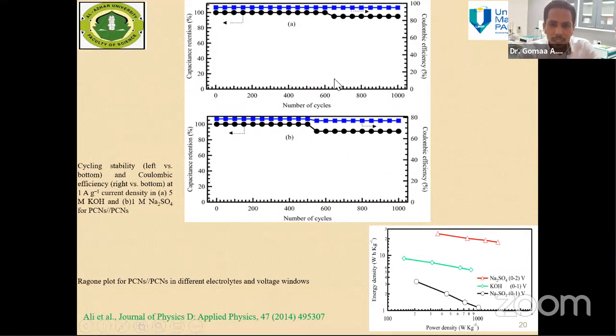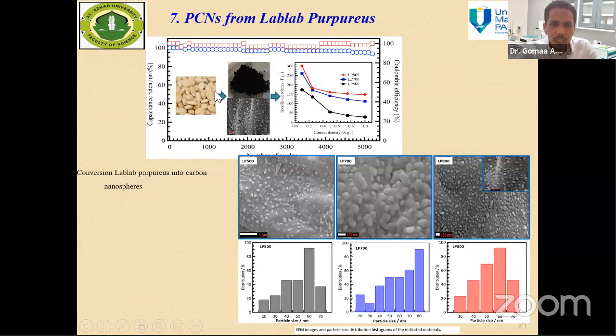Another example for carbon material prepared from agriculture waste is porous carbon nanosphere prepared from a different precursor. So from this agriculture source, we successfully obtained carbon nanomaterials at different calcination temperatures, or different pyrolysis temperatures, 500, 700, 800, and most of them showing the spherical particles of the carbon material, and here the particle size distribution showing the nano range size of this material.